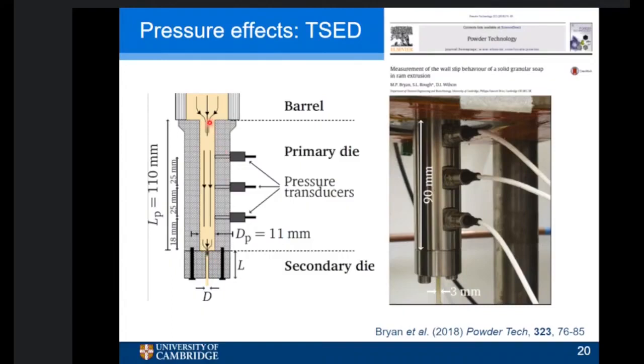And if we want a big pressure, we make the secondary die longer. So that means we can work at the same velocities, and we can manipulate the total pressure independently of that. The other advantage of this system is that by having this first die entry, we're also shearing the material, so it's actually in its flowing state, which is what we want to make the measurements on, rather than in the pre-compacted system in the barrel.